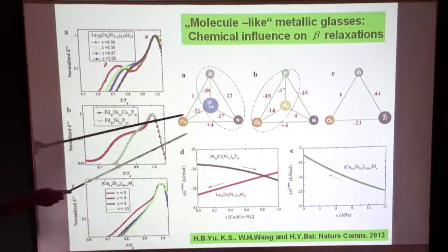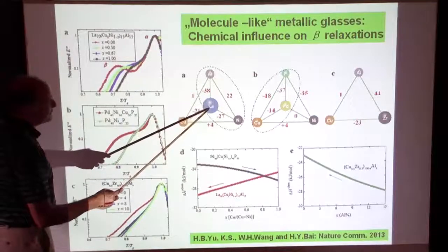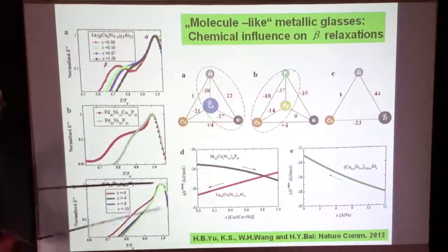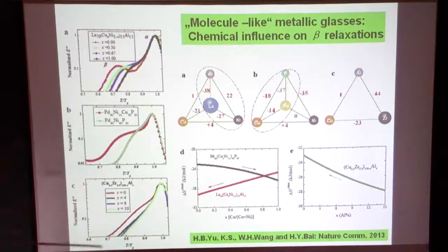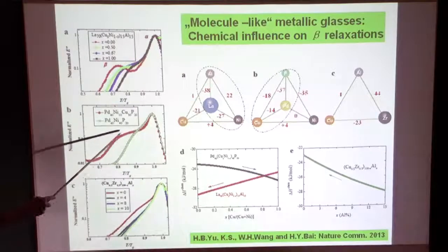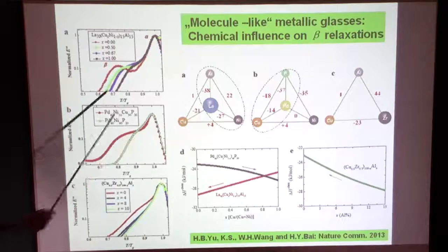And so these kinds of systems, which are the early transition metals compared to the late transition metals, have additional cutters, or we call them cutters and glues. So in one sense, it depends on which element you choose and in which kind of matrix it is. Sometimes you can have a glue between different clusters and form superclusters, which then show up as a separate peak. And sometimes you have a cutter in between. We call it a chain. The string, which I'll show in a minute, is then actually cut into smaller ones, and then the system is shifted over to underneath the alpha peak.